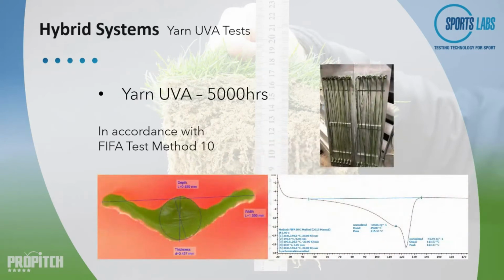The tensile strength of the yarns is measured before and after the 5,000 hours exposure, and the change in tensile strength is calculated. Currently, FIFA and World Rugby require 3G systems to meet a maximum 25% change. The change in colour is also assessed and categorised using a grayscale of shade.